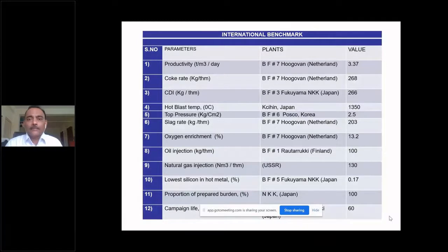One of the furnaces of Netherlands, furnace number 7, Hoogovens. Hoogovens is the design of the stove. Their productivity, they got 3.37 tons per meter cube per day. In the same furnace, their coke rate is 268, very small. I'll come to the picture of Bhilai also. The 268 kg per ton of hot metal is very small.